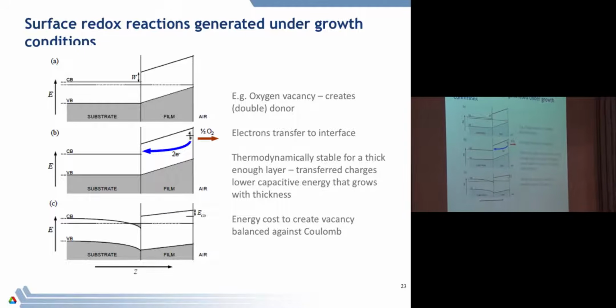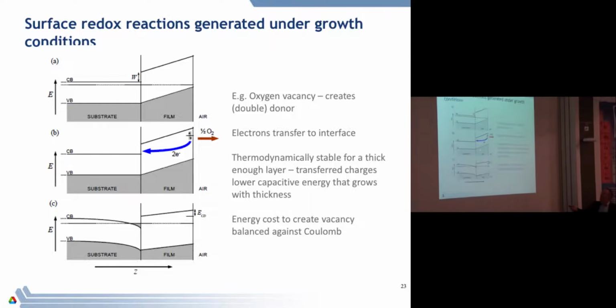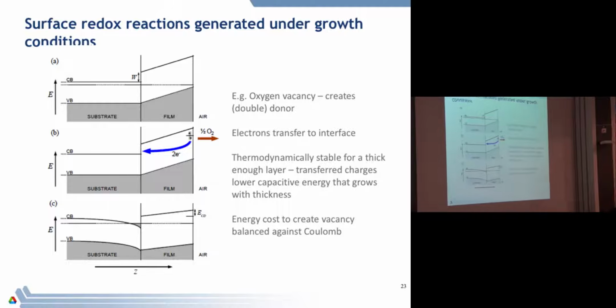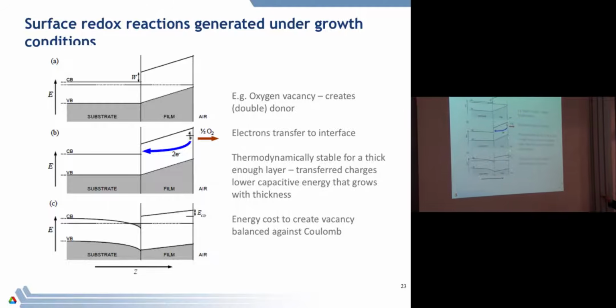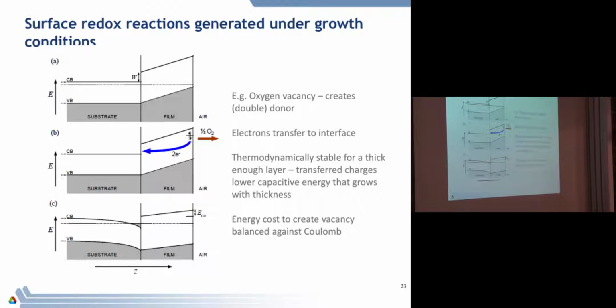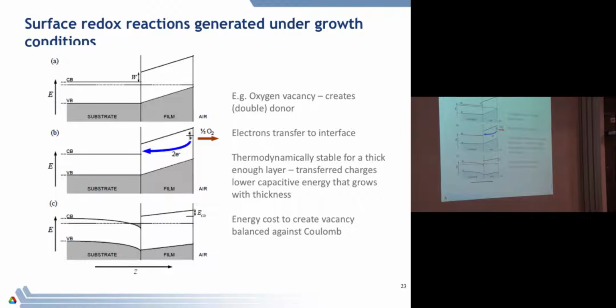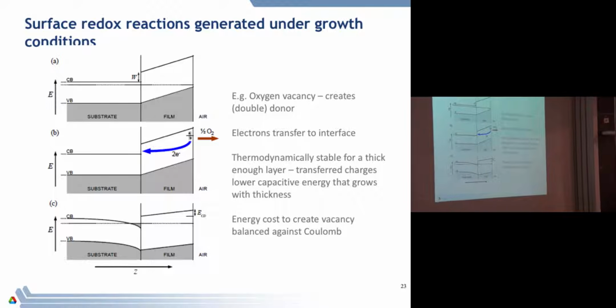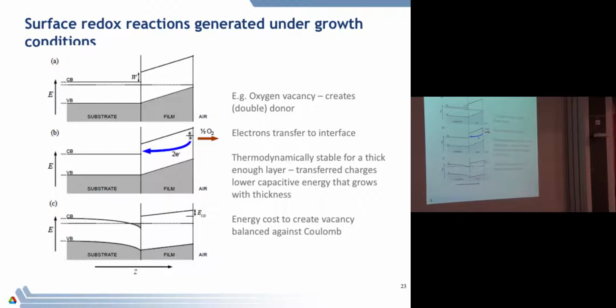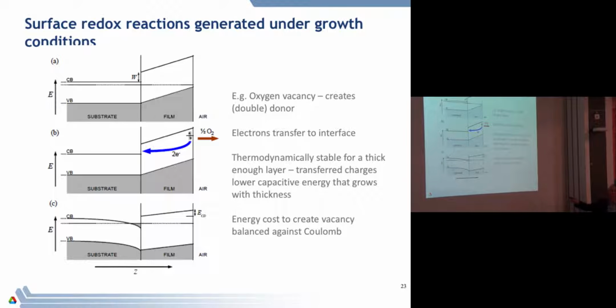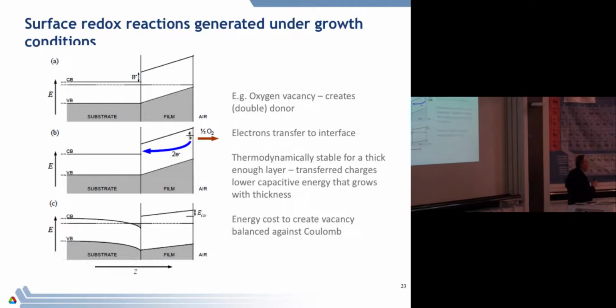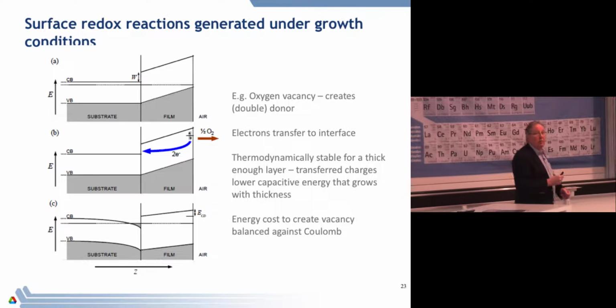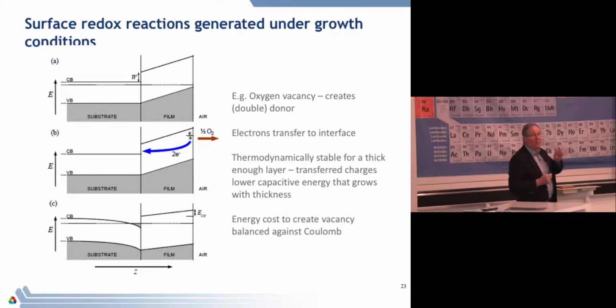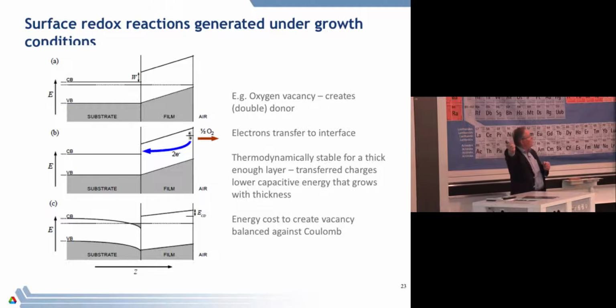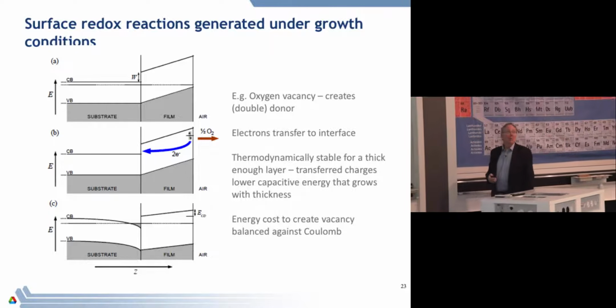Why not? Well, one of the processes that can get in the way is to think about, as you're growing, there are other things that could happen. So you have a surface that you're growing and you're depositing all of the time. Does it want to be stoichiometric? And why might it not want to be stoichiometric? So one simple thing is just to think about what would happen if you lost an oxygen atom from the surface. If you lose an oxygen atom, it's naturally an O2 minus in the structure. So if you take an atom away, you're going to leave 2 electrons behind.